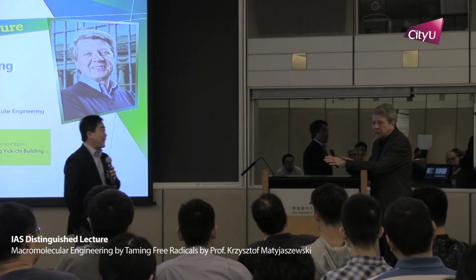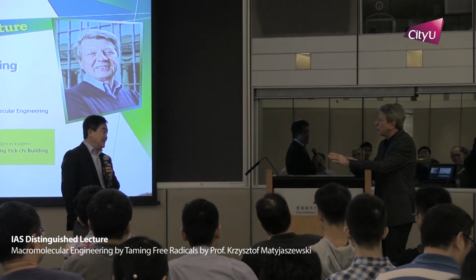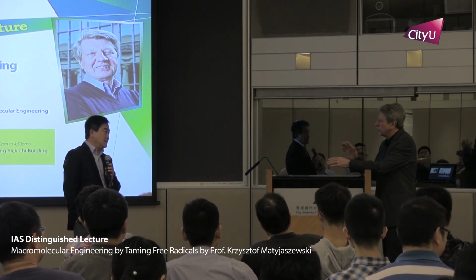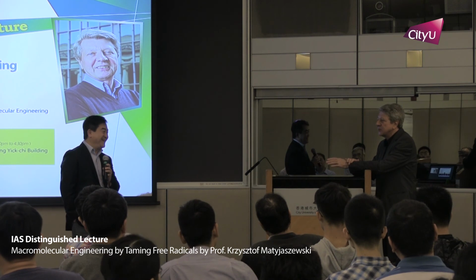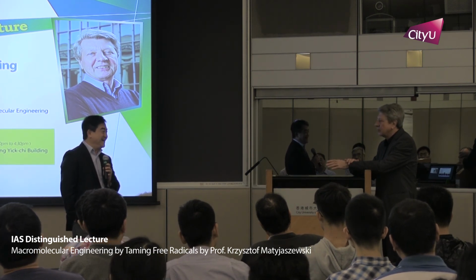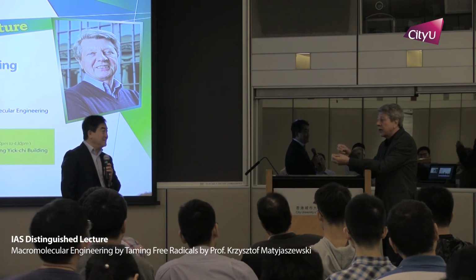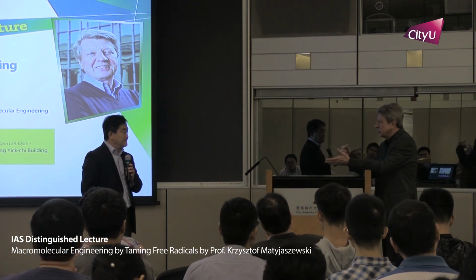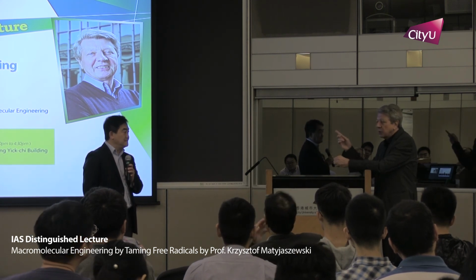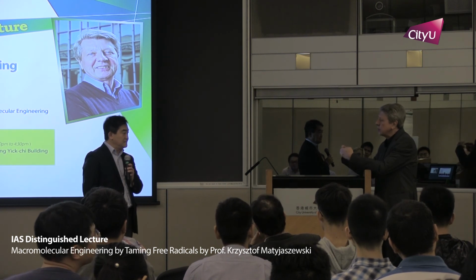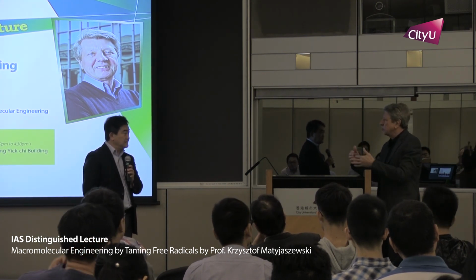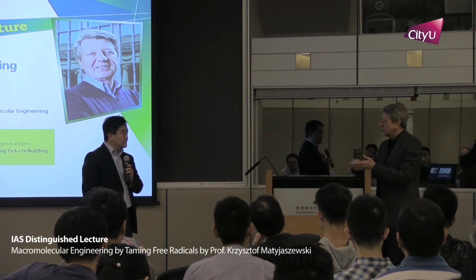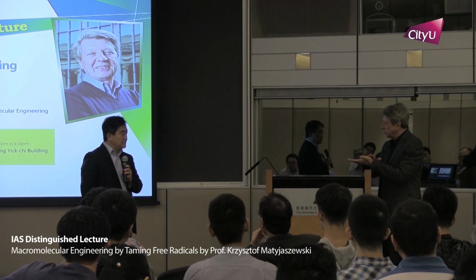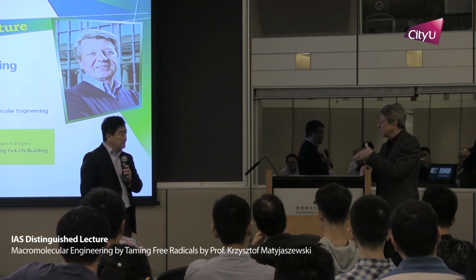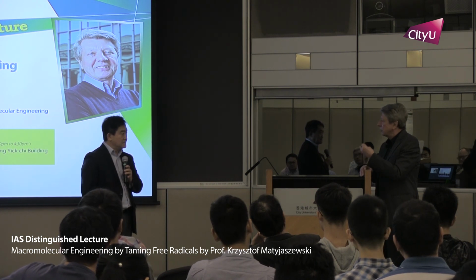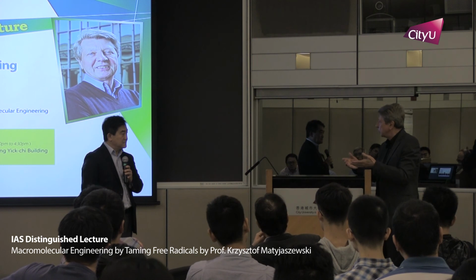So there are really two approaches. One therapy now is that people inject hyaluronic acid, and it works, I don't know for yogis, but I had some colleagues who say for 2 weeks it works, and then it doesn't, because hyaluronic acid is degraded by enzymes such as hyaluronidase and it is gone. So one example I showed you was these brushes. These brushes are based on phosphorylcholine, which is a biocompatible material. We started doing that, of course, in vitro, and first it was on this mica surface. There are now some studies on the biocompatibility. We would not like them to degrade too fast because you would like to have maybe one injection only.